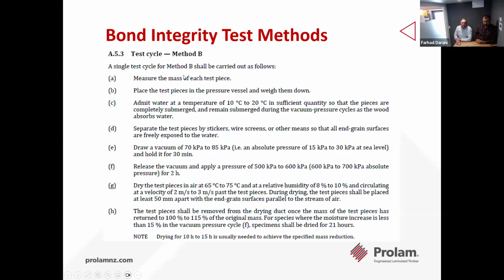I won't bore you with going right through that, but essentially we have a pressure vessel where you fill it up with water. We put the timber in there, we pull a vacuum of 70 kPa to 85 for 30 minutes. And we release the vacuum and then pressurize it. And then we dry the pieces in an oven, and then we count the delamination from there.